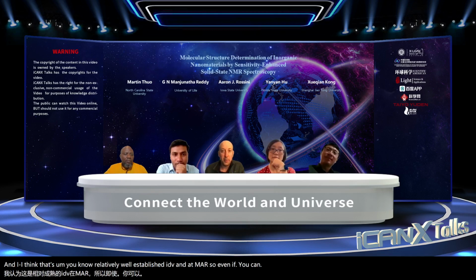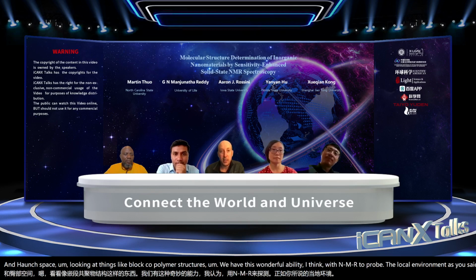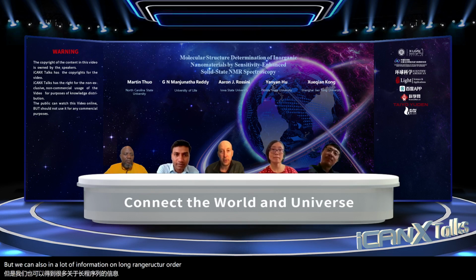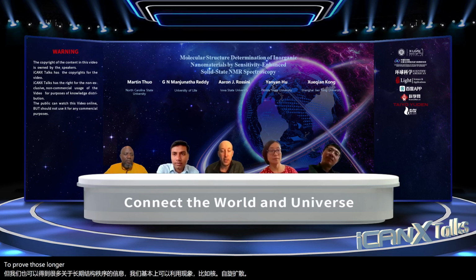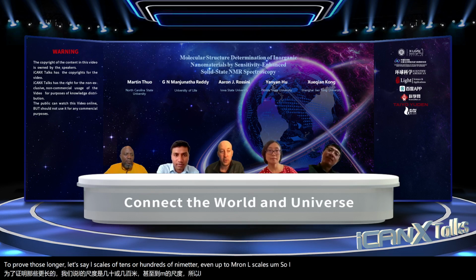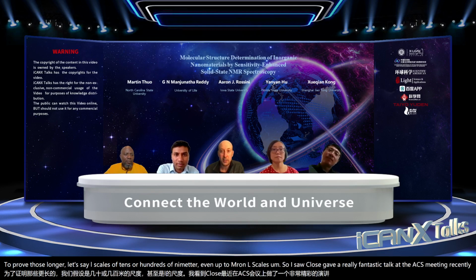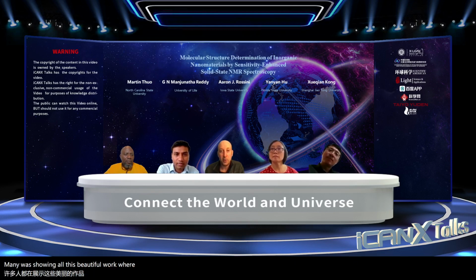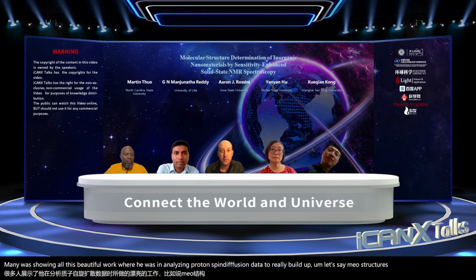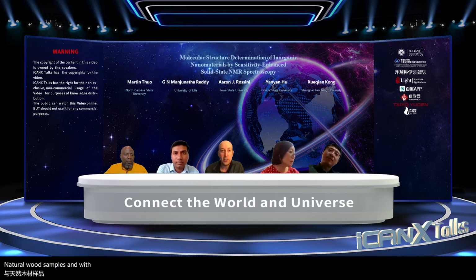Yeah, and I think that's a relatively well-established idea in NMR. Even if you go back to the classic work of Schmidt-Rohr and Hans Spiess, looking at things like block copolymer structures, we have this wonderful ability with NMR to probe the local environment, as you said, but we can also get a lot of information on long-range structural order, and we can exploit phenomena like nuclear spin diffusion to probe those longer length scales of tens or hundreds of nanometers, even up to micron length scales. So I saw Klaus gave a really fantastic talk at the ACS meeting recently, and he was showing all this beautiful work where he was analyzing proton spin diffusion data to build up mesostructures of natural wood samples. And with DNP, we have that same opportunity.